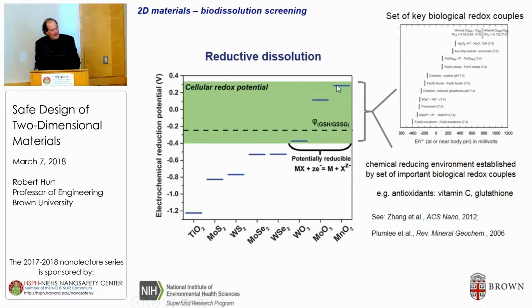And here we go. There's manganese dioxide. It's extremely susceptible to reductive dissolution. So when we finished this in silico data mining exercise, we had the idea that most of these 2D materials would not be stable, not thermodynamically, but kinetics mattered. So what we needed were data.